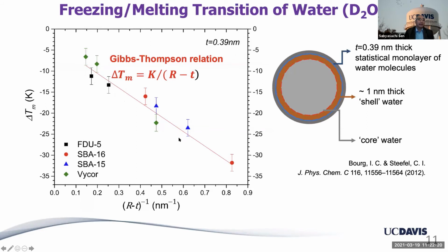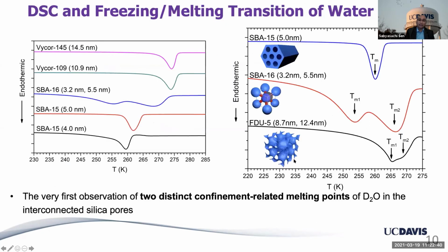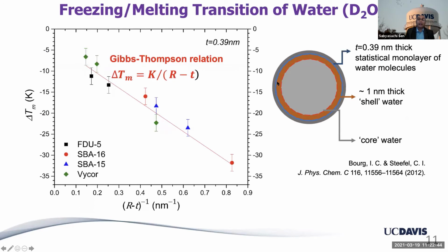So with that, you can see a nice relationship that follows the Gibbs-Thomson relation. Here, K is a constant that actually includes, for example, the enthalpy of melting and molar volume of ice and those kinds of parameters. So this is nice, but also what Bourg and Steefel saw is this brown layer, which is about a nanometer thick, where the water is highly structured, they found in their simulations. And they called it shell water as opposed to the core water at the center of the pore, which is more like bulk water. And they said that the shell water is highly structured because of its strong interaction with the interface, and so it must have a slow dynamic compared to the dynamics of the core water.